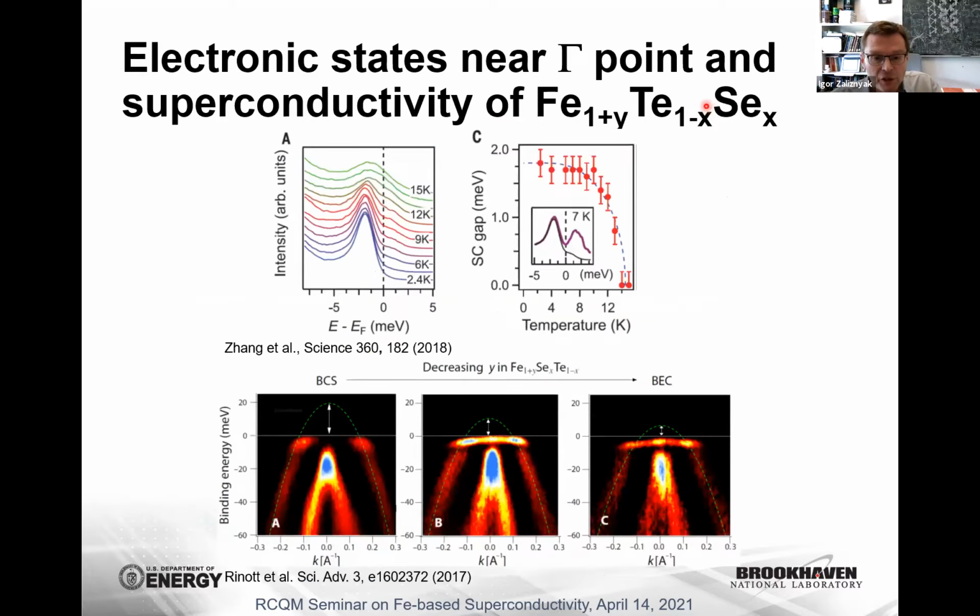In the presence of superconductivity, the superconductivity in ARPES shows up as this superconducting condensate peak split off the Fermi level by a superconducting gap. This is this bright flat feature here. So this is a measurement on the same series of materials, also by Kanigal's group. And I'm showing this measurement here because we will use this feature to quantify the presence of superconductivity in our sample, in our work.